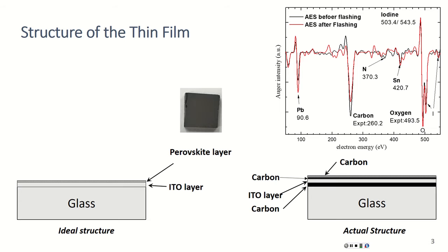in both cases, if we flash the samples to high temperatures, they tend to get destroyed. So we couldn't go beyond 400 Kelvin, even 380 Kelvin. It starts to deform the film. So we didn't want to dissociate those films.